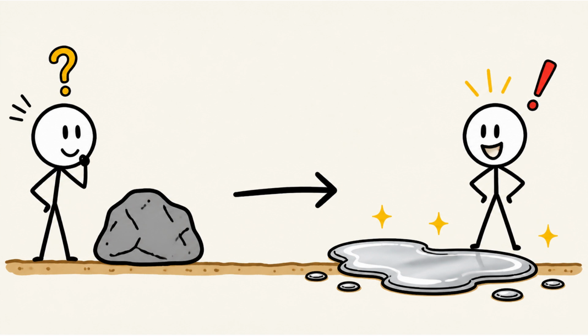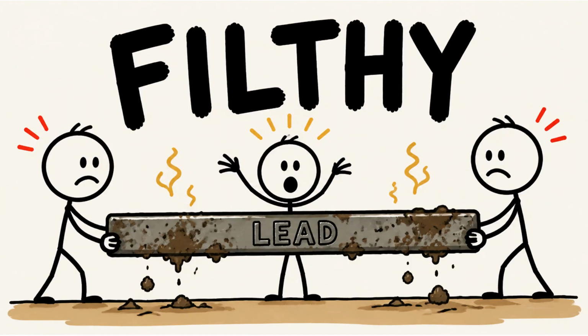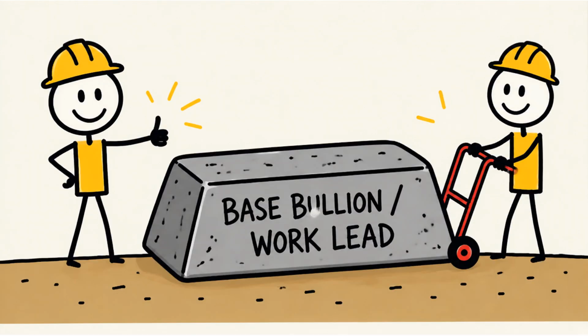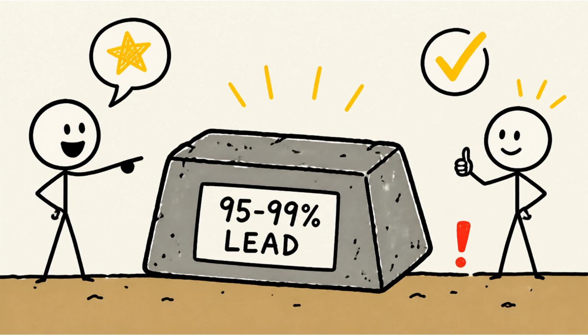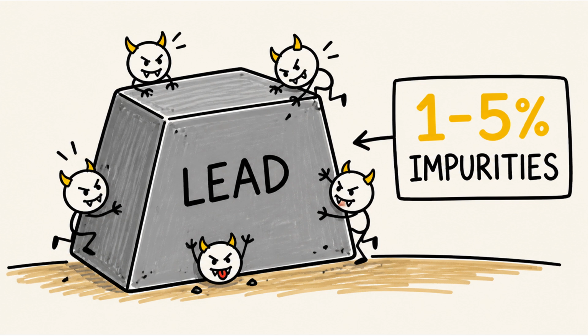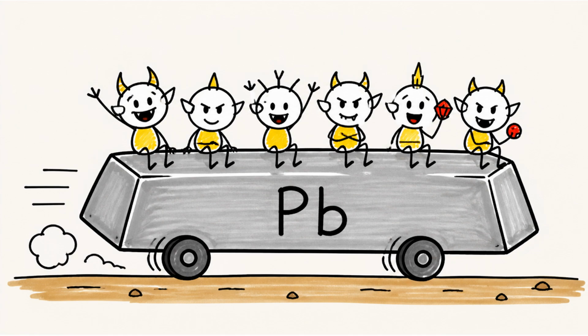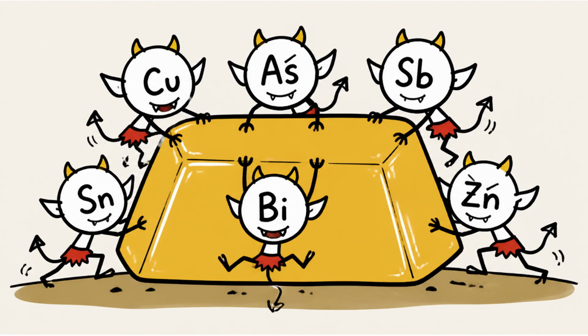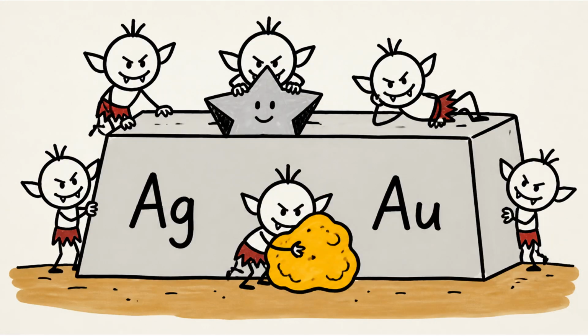You started with lead sulfide inside a rock, and you ended with a puddle of actual liquid metal. But, and this is the part people skip, that metal is filthy. What pours out of the blast furnace is called base bullion, or work lead, and it's only about 95 to 99% lead. That last 1 to 5% is a stew of other metals that were hiding in the ore the whole time and came along for the ride. Copper, arsenic, antimony, tin, bismuth, zinc, and remarkably, silver, and even a little gold.